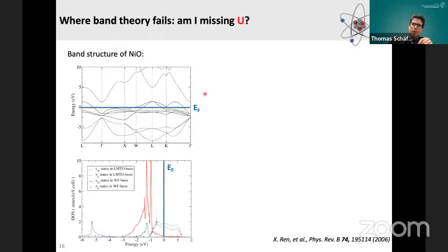This we can also see when plotting the so-called density of states. And the density of states is the projection of this band structure onto this y-axis here. And it tells you how many states you have per energy spacing. And you see again, at the Fermi level, we have, out of the band structure calculation, some weight. So both plots tell you that this compound should be a metal.